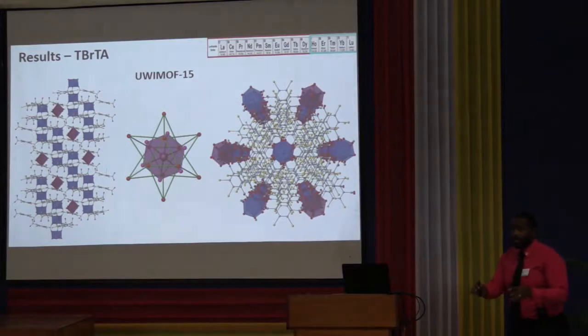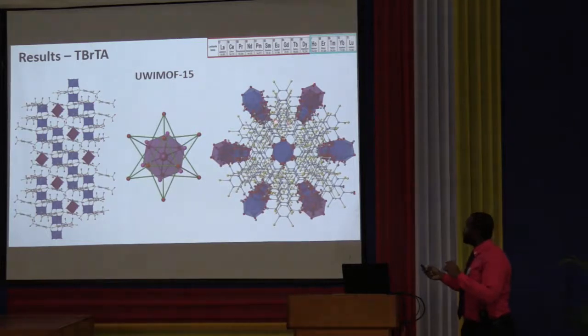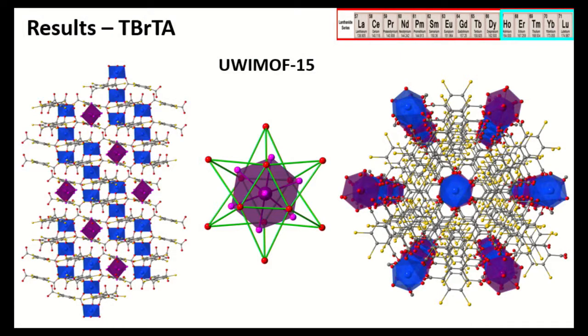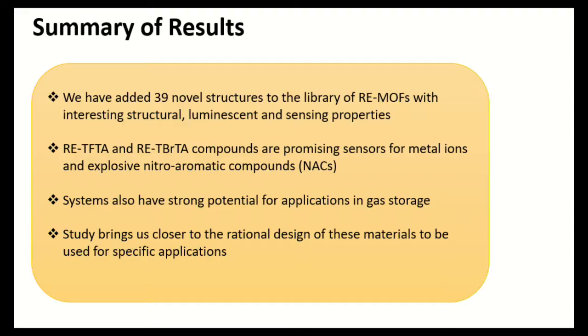Finally, ladies and gentlemen, I'm out of time, but I must draw your attention to UWIMOF-15. This system is a 3-dimensional coordination polymer that traps rare earth octahydrate clusters. These clusters are surrounded by 12 hydrogen-bonded water molecules to form a 3D Star of David cage. Water clusters are important, especially when they are trapped in these systems, because they allow us to study the behavior of bulk water. So we'll be looking at those studies in the future for this compound.